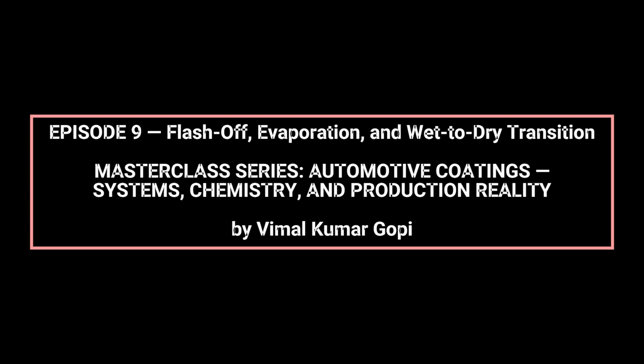Fast solvents drive early viscosity increase and rapid skin formation, while slower solvents maintain film mobility for leveling and orientation. The balance between these fractions determines how long the coating remains flowable and how quickly internal diffusion pathways close. Poor balance results either in premature skinning or excessive openness.